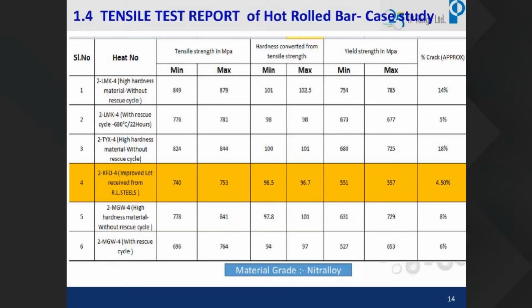Then we introduced yield strength as one of the criteria. If you see the sample, we made a study throughout the bar also, and we could see there is a lot of heterogeneity, which we communicated, and we finally got it rectified in the microstructure as well as in the mechanical properties. And we could also manufacture the product with less than 5% crack.